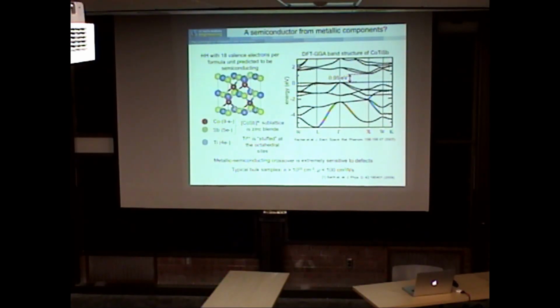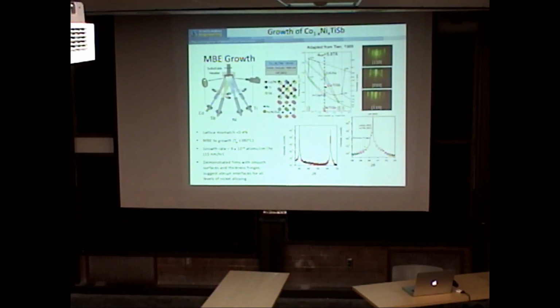So we try growing this material. What we've done is use indium phosphide, grown an indium aluminum arsenide, indium gallium arsenide buffer layer, and then transferred down and grown this cobalt titanium antimony, or cobalt nickel titanium antimony. I'll talk about cobalt titanium antimony today. The diffraction pattern looks nice from the RHEED. We can see nice interference fringes in the X-ray diffraction, saying it looks like a good single crystal film.